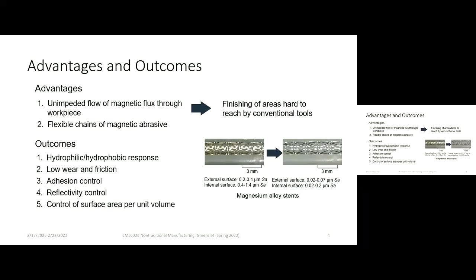And then on the internal surface, we were also able to get a very good surface finish. It started off initially at 0.4 to 1.4 microns, and now we're at 0.02 to 0.2 microns. So it's very effective for this magnesium alloy stent.